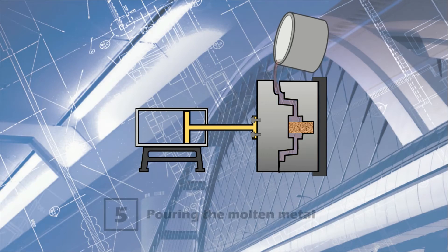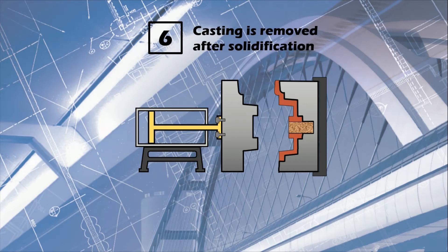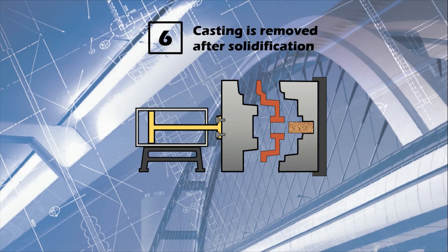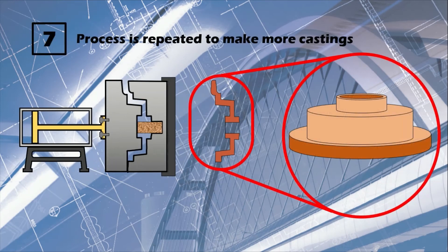After installing the required core, the next step is to pour the molten metal into the mold. After solidification, the mold is opened and the casting is removed to reduce the chances of hot tears. The process is then started all over again; preheating is not required because heat from the previous casting is adequate. The refractory coating should last several castings. Since this process is usually carried out on large production runs, automated equipment is used to coat the mold, pour the metal, and remove the casting.